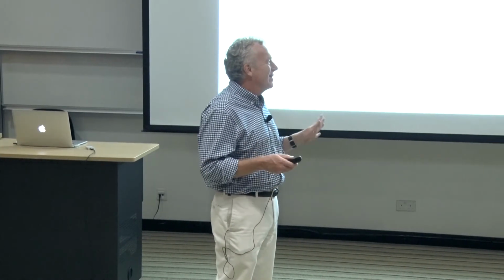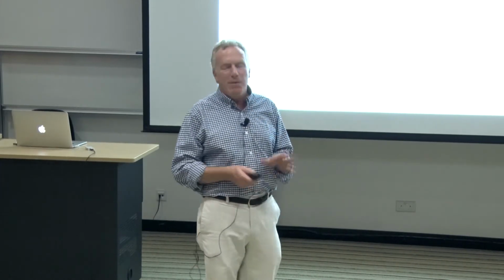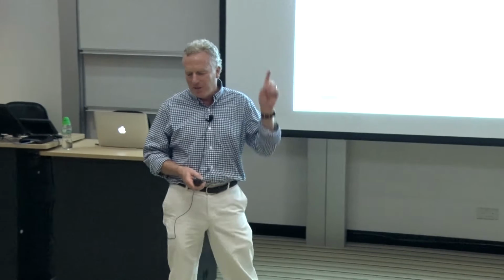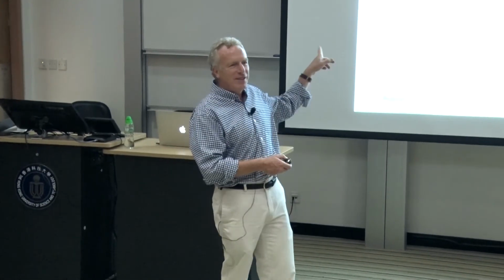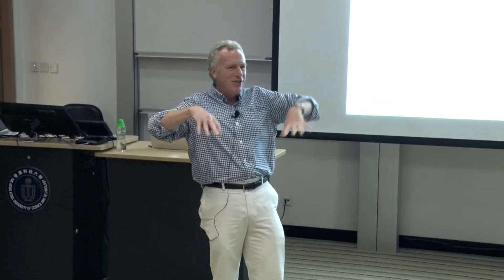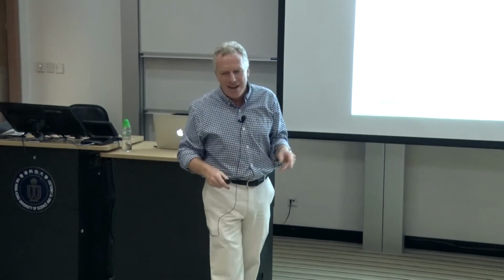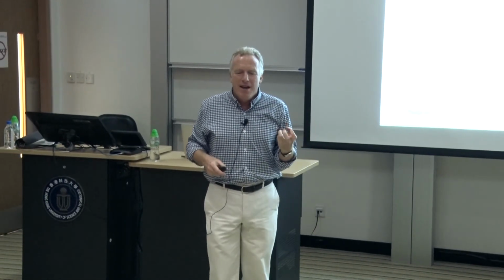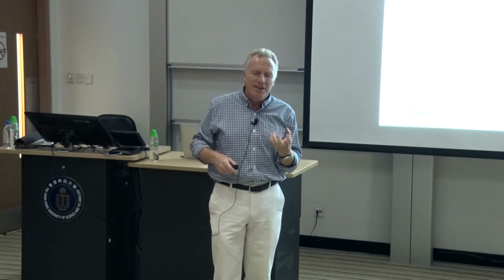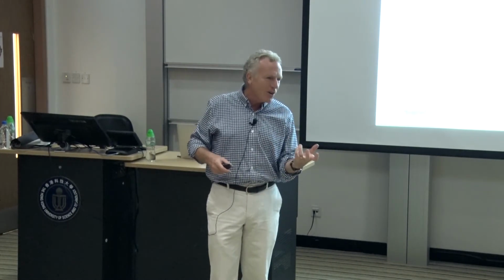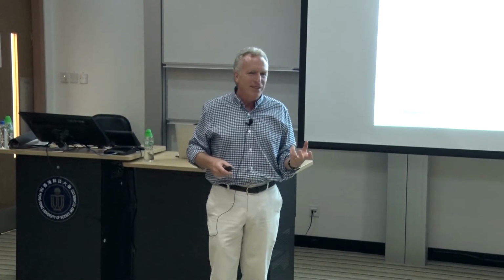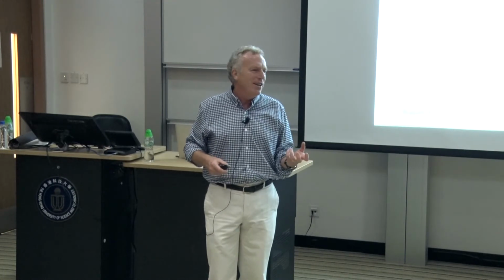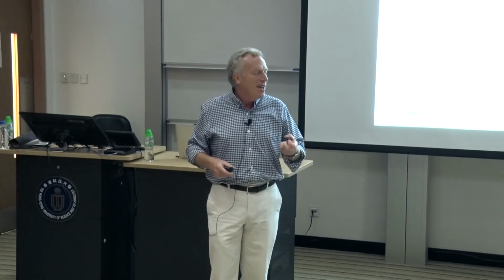The entropy that they calculate has nothing to do with the entropy in this material. This is closely related to my diagram of the wiggly energy and the molecular dynamics. When you calculate the entropy of the material, you essentially count the number of states. The simplest model is you count the number of states. But the material actually has to visit those states in order for it to be meaningful as the entropy. Otherwise, it's a constrained material.